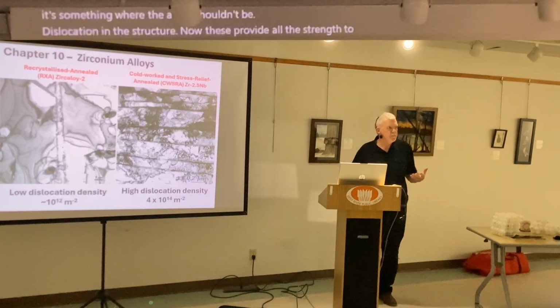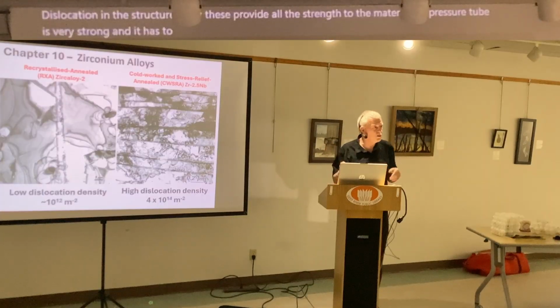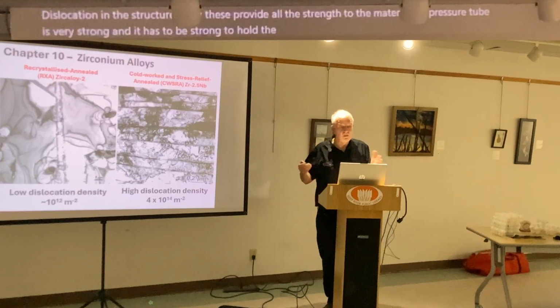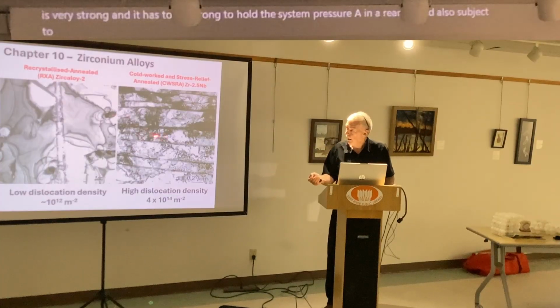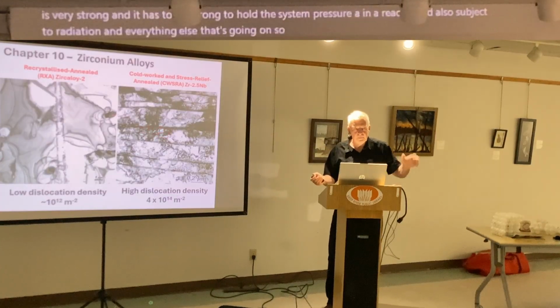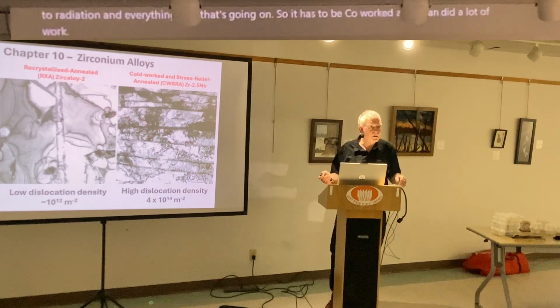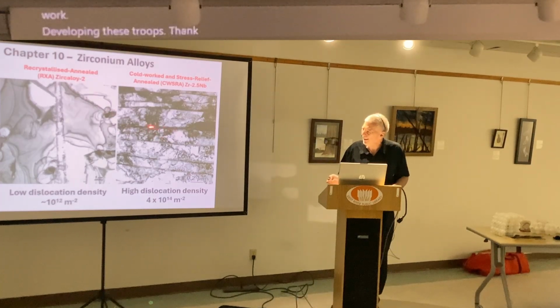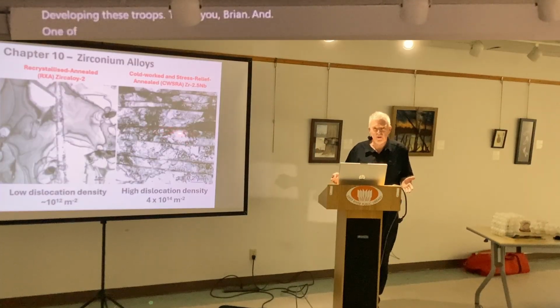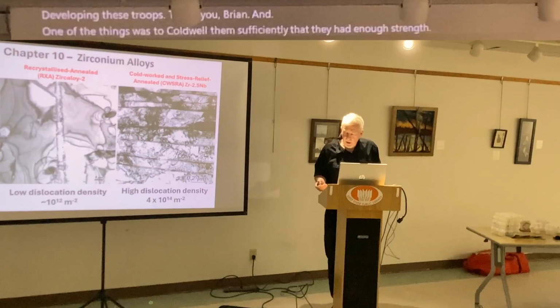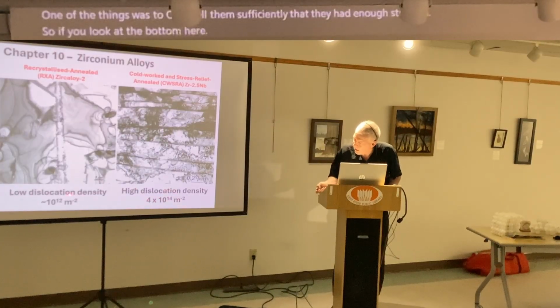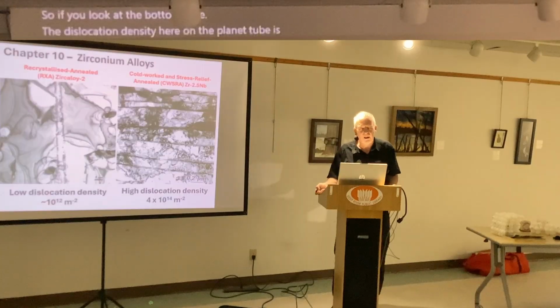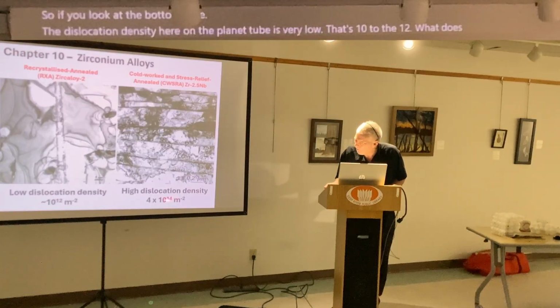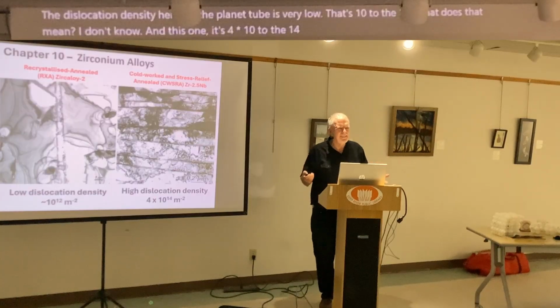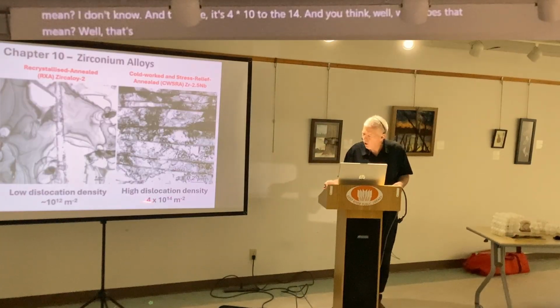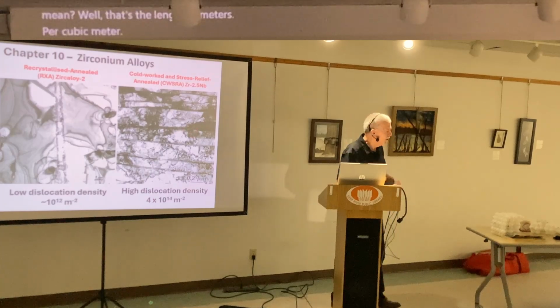So a pressure tube is very strong. It has to be strong to hold the system pressure in a reactor, and also subject to radiation and everything else that's going on. So it has to be cold worked, and Brian did a lot of work developing these tubes. Thank you, Brian. One of the things was to cold work them sufficiently that they had enough strength. If you look at the bottom here, the dislocation density on the Calandria tube is very low, 10 to the 12. And this one is 4 times 10 to the 14. What does that mean? That's the length in meters per cubic meter of this material. So what does that mean?